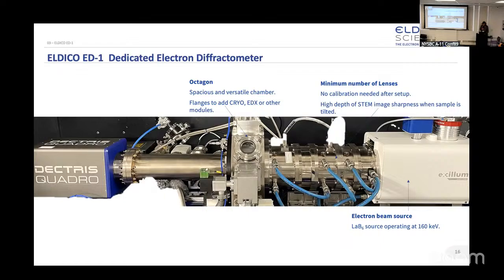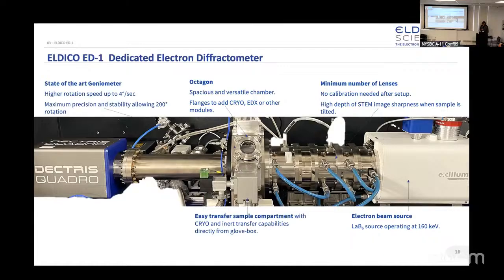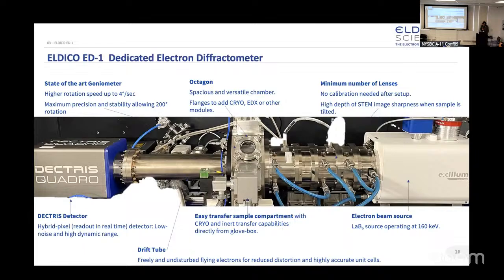and the sample is imaged by a STEM. They have a large goniometer chamber for cryo and EDX and so on. And as I said, they focus a lot on the goniometer to allow for high speed and for a large angular range to minimize the missing wedge. And they have our detector in it, which can go to 4.5 kilohertz, and is an integral part of the design.